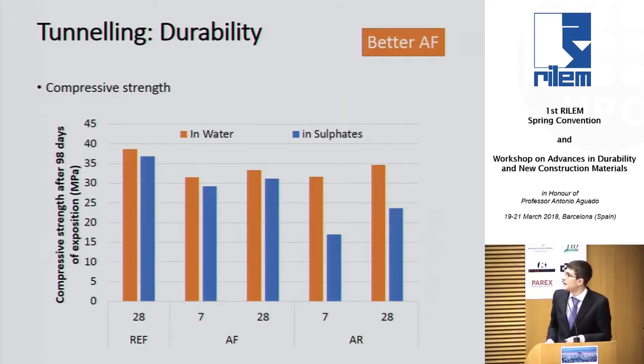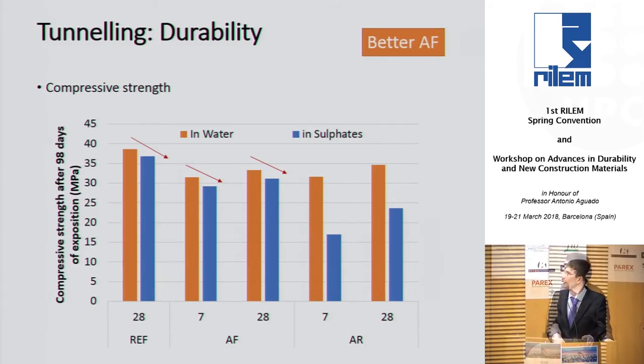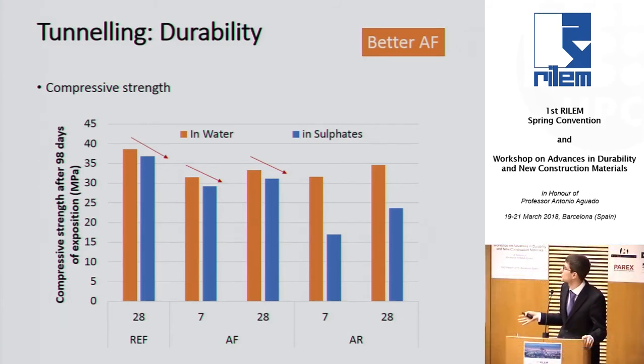Here you see the results of compressive tests made on sprayed samples, produced with the reference one here without any accelerator, and the other two groups here: you have an alkali-free accelerator used to spray in order to accelerate the hardening process as commonly done in tunnels, and you have an alkali-rich accelerator, right? The orange bars are tested in water, no sulfates. The blue bars are tested in an environment with a lot of sulfates. And what we see is a reduction in strength as a result of exposition, many days of exposition. I think in this case it was almost 100 days of exposition to sulfates.